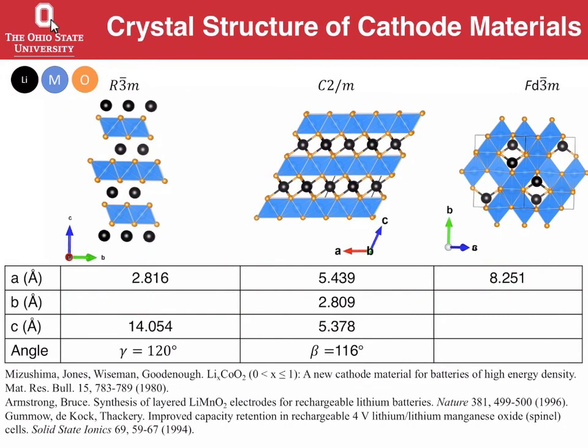Okay, so the structures that you'll be working with, right? Lithium cobalt oxide, R-bar 3M, this is the pristine. You also have your choice of C2M and this spinel lithium manganese oxide. So you have a choice. Lithium nickel oxide will be coming. So you need to know what is your starting crystal structure and how is that going to change? And where is it going to change? Where would you expect it to change based on our discussion just now? In your voltage, what would you expect to see, in terms of a change in your voltage profile? Deep thought, I see. Okay. Well, when you get into your group, you can discuss as a group what you should be seeing and where you need to stop the cycling.